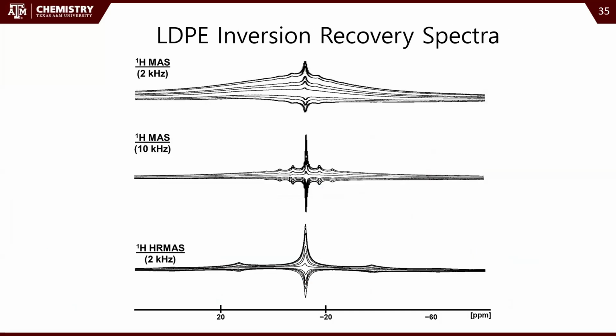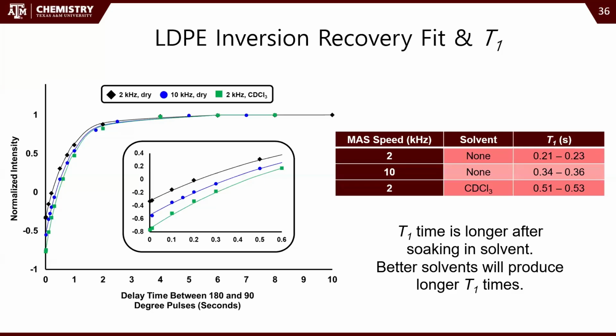So we did that for a couple different materials, and you can see all the stacked spectra here, and we plug all of that data in, and we get pretty good fits. And you can see our T1 time is in the kind of quarter second to half a second range. So as a dry material with 2 kilohertz rotational speed, we're about 0.2 seconds. And when we soak it with chloroform, which is kind of the best performing HR-MAS solvent, we see an increase up to about half a second. So that's showing that we have a good degree of increased mobility.